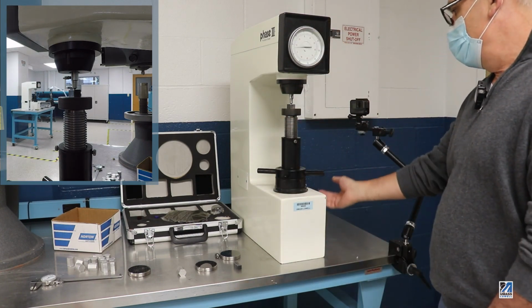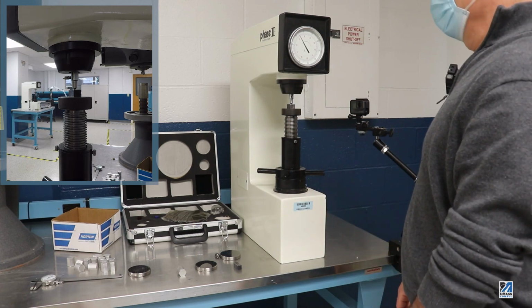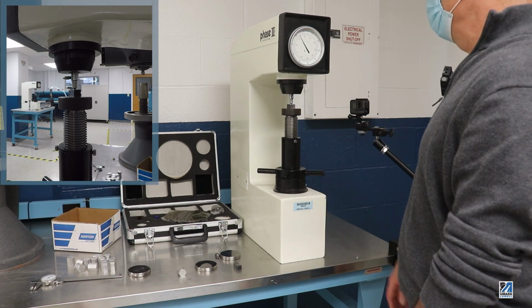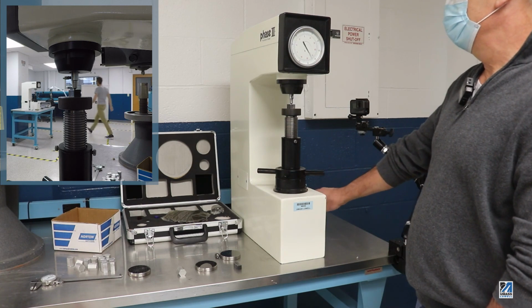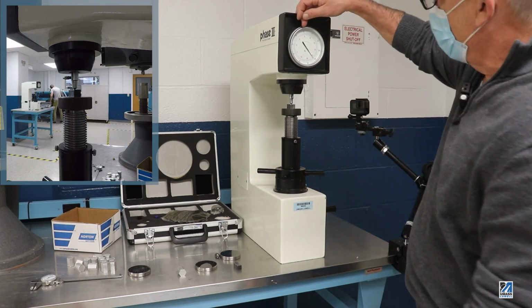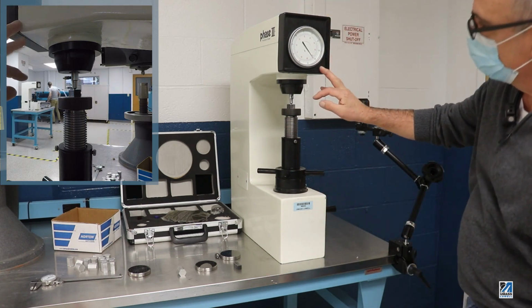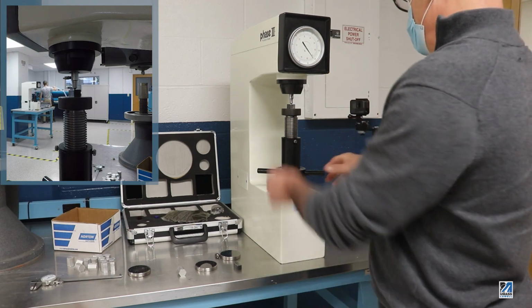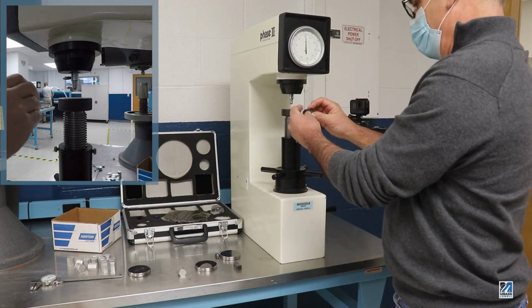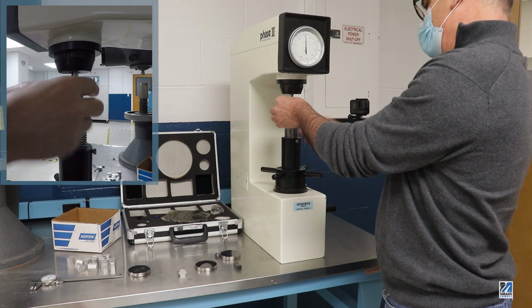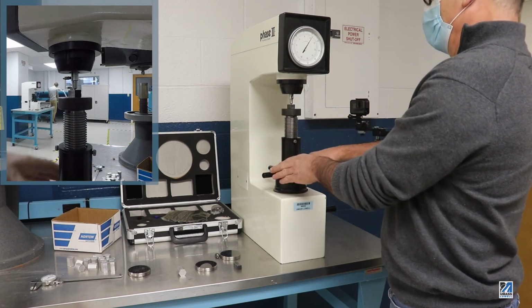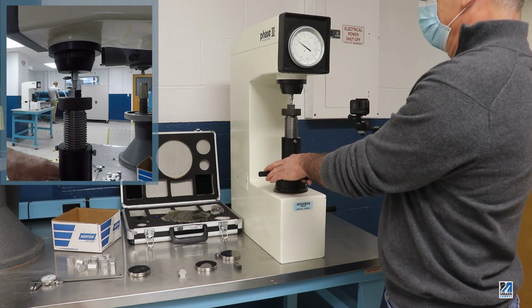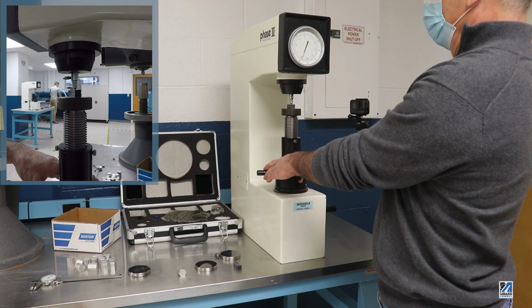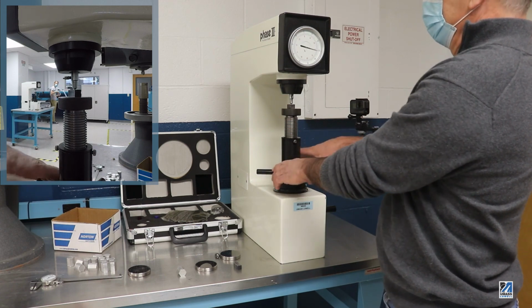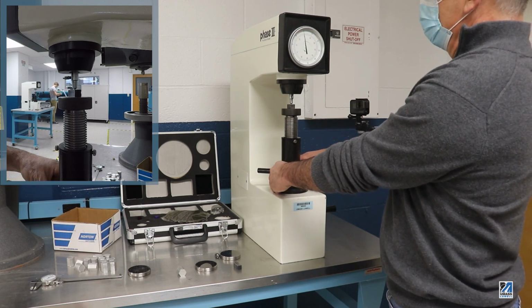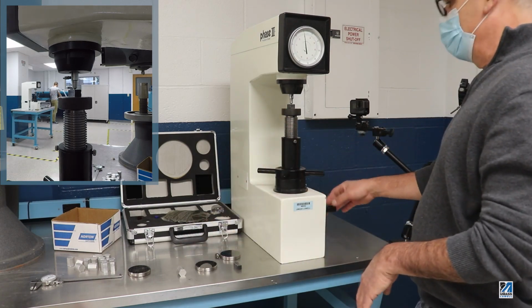Minor load is applied, apply my major load, remove the major load, and I'm on a Rockwell C of approximately 41.5. As an experimentalist, what you want to do, statistically speaking, is obviously take a couple samples just to see if it's repeatable, or if there's regions that had a heat treatment to them that then is different from another region on that same sample.